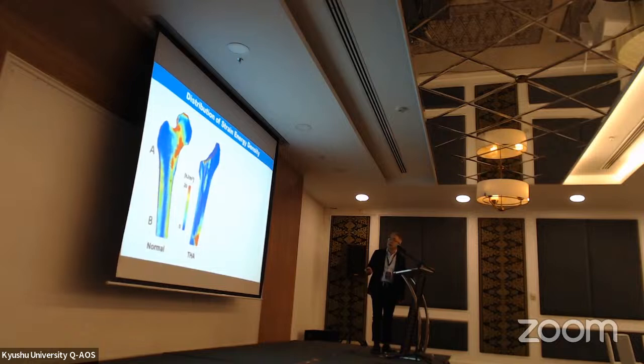So we can see the high concentration. This red portion is a high concentration of mechanical energy. It's a strain energy density. So then after THA, we lose the mechanical energy like this.